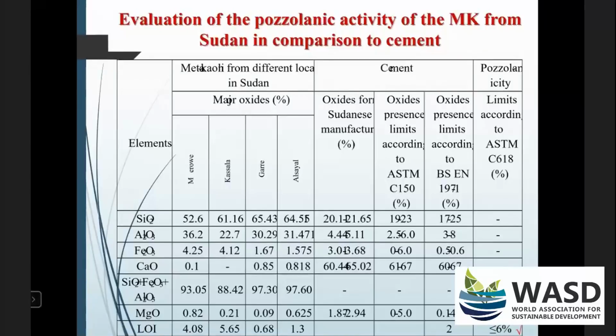On top of this, we had to check the pozzolanicity and the limit set by ASTM C618. So what we found out is that the kaolinite clays are very rich in oxides that are of interest to us when we study cement.